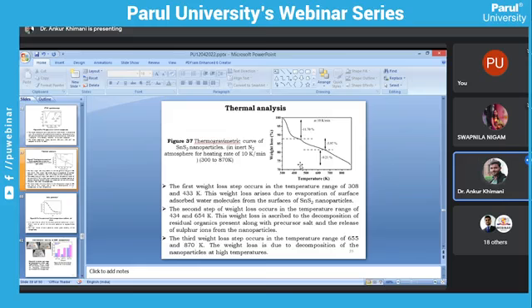Thermal analysis. TGA of the particular sample has been done, and we have the TGA graph, that is weight loss versus temperature. We have weight loss in three steps. First is minus 11.70%, second is minus 5.97%, and third one is minus 9.21%. So three steps are observed in this TGA. The first weight loss step occurs in the temperature range of 308 to 433 Kelvin. This weight loss arises due to the evaporation of surface adsorbed water molecules from the surface of the SnS2 nanoparticle.